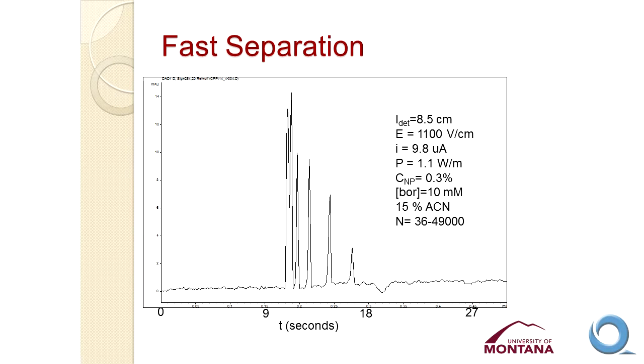Why is it important that the nanoparticles do not conduct any current? Well, here what we're doing is in a relatively short capillary with very high field strength and still very low current. Most of this current is carried by the borate buffer and not by the nanoparticles. We're able to separate those same five ketones in less than 20 seconds. So we can do very fast separations, still with very high efficiency, somewhere around 40,000 theoretical plates for these separations.